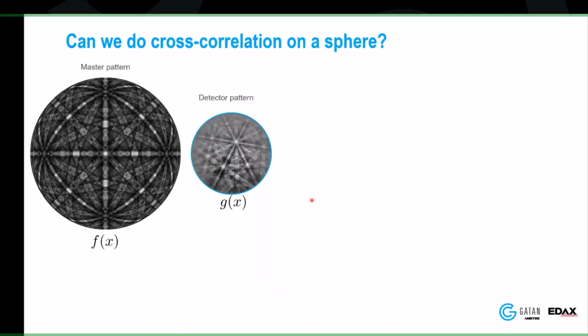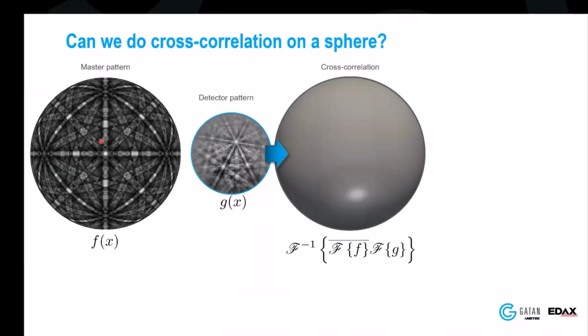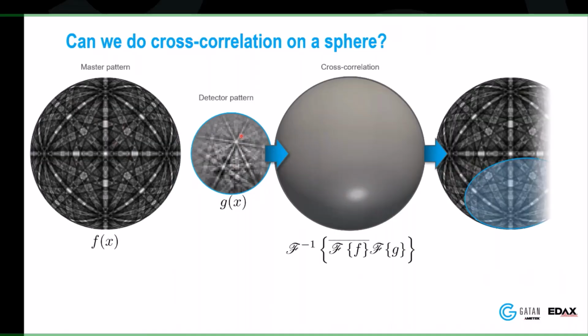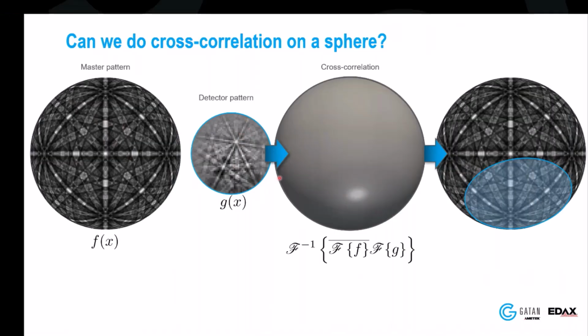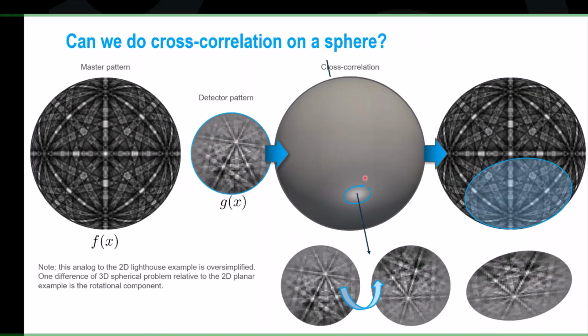But what if I could do it on a sphere? Well, because of the way EBSD works, if I have this master pattern, I can then do a cross correlation of my pattern from my experiment and figure out what this is. This is basically what spherical indexing is doing. We're taking our master pattern, we're doing our detector, and we're doing a little bit of fancy math on the end, because this circle here is a projection onto the master pattern based on the geometry. So this pattern right here actually comes from down here. So we have to do a couple of distortions, or, what's the best word for this? Someone called it a transformation from our patterns to be able to correlate it more closely to the actual master pattern. So this is what we're doing behind the scenes when we're doing this spherical indexing.